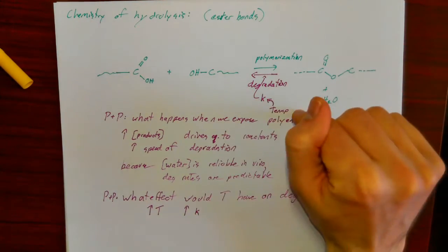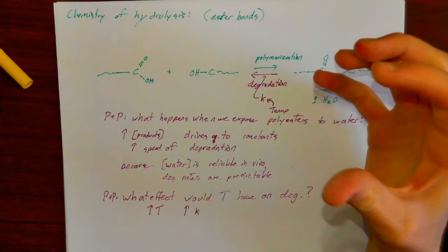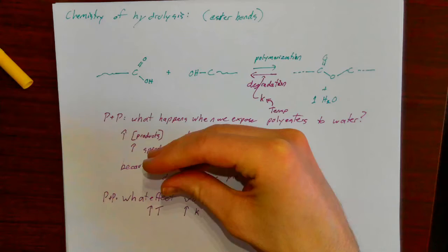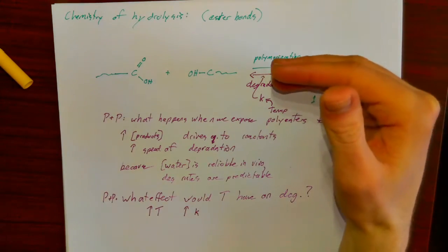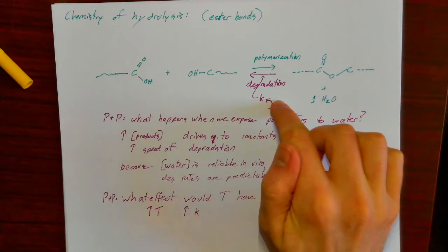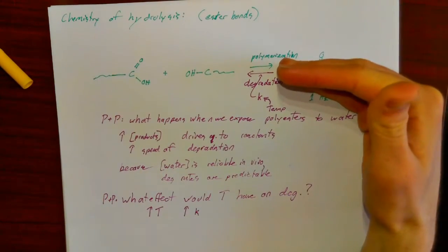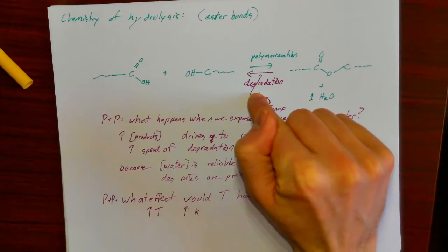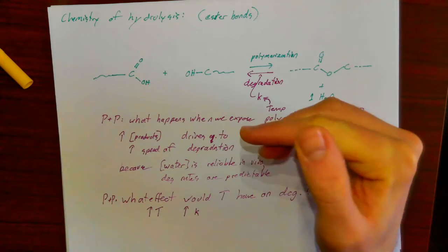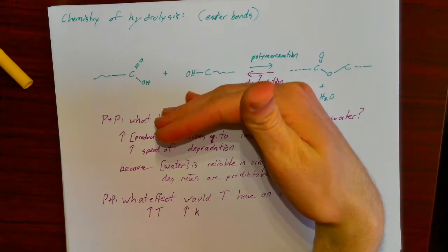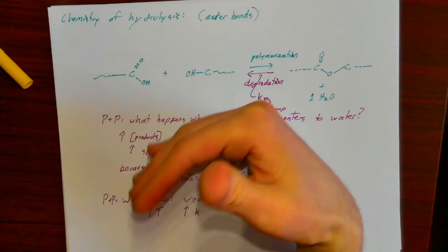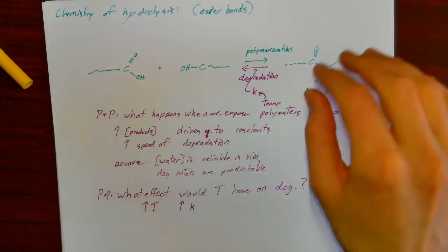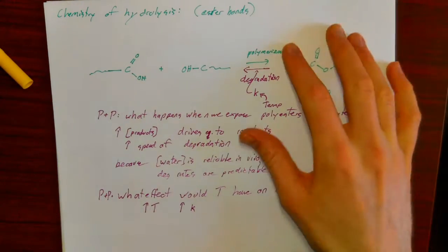Now, sometimes if you want to predict the lifetime of a device over decades, but you don't want to wait decades to see if your device will last that long, you can artificially increase the temperature beyond what you expect it to be, and then use mathematical models of how temperature might affect K to basically say, hey, this lasted 1 year in this higher temperature accelerated degradation environment, so I could predict it would last 10 years in a normal environment, something like that.